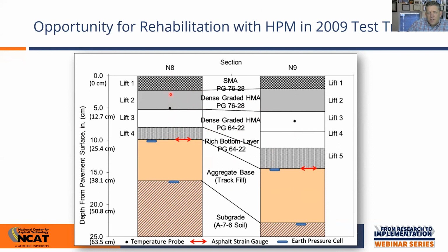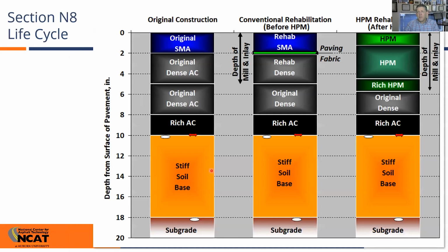So the difference here essentially is that we had 10 inches on top of that poor soil that Buzz mentioned, that we imported. We had 10 inches of AC in section N8 and then 14 inches of AC in section N9. And what I'm going to focus on is section N8 because, as we were hoping to see, and what Oklahoma DOT was wanting to see, is that we would see failure in N8 and not see failure in N9. We saw a lot of failure, and in fact got to a point where we had to operate in almost emergency mode to be able to continue putting traffic on the section.